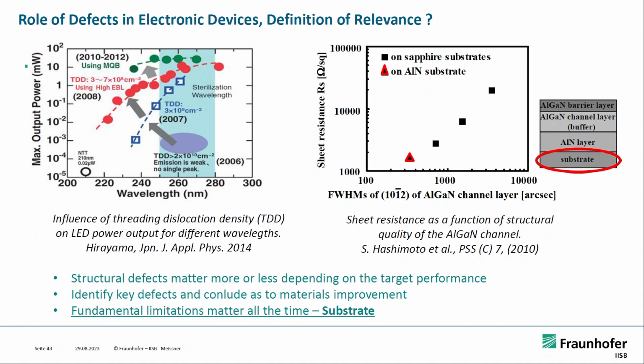If you want a higher performance on your device, then it's getting an issue. So if you say, okay, now I want a UVC LED and I want, let's say, 220 nanometer or 230 nanometer, then you see all the curves drop down drastically, which means that the output of your device, like you want to shine light out of it, extract a lot of photons out of your device, won't function so nicely anymore because you have a high number of dislocations.